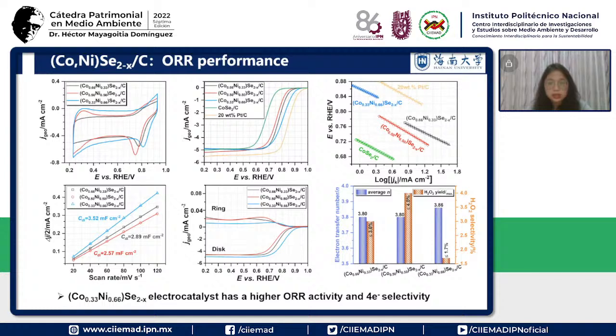But this is close to the commercial platinum catalyst. And then we continued to test the RDE to find some information about the selectivity. We can also see here that this 1:2 material shows high 4-electron selectivity, based on the average electron transfer number and the hydrogen peroxide production. So we can say this material has a high ORR activity and 4-electron selectivity.